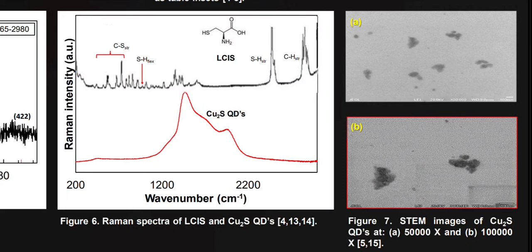But agglomerations can occur for copper nanoparticles due to instability at temperatures over or below 25 degrees Celsius, reaching scattered values of diameter that can even be close to 150 nanometers at 40 degrees, for which better care is suggested when handling STEM samples. All the previously discussed techniques were done in the same laboratory where the temperature is around 25 degrees Celsius.